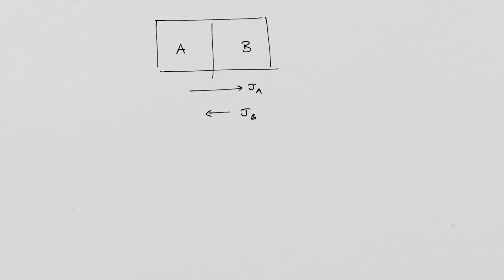They may have different sizes, different migration energies. So I've drawn the case where A atoms diffuse more rapidly than B atoms. So what happens in this situation? You've got this thing on your desk. Heated it up. Diffusion is happening. A atoms are going over to the right hand side, B atoms going over to the left hand side. But the rates are not the same.